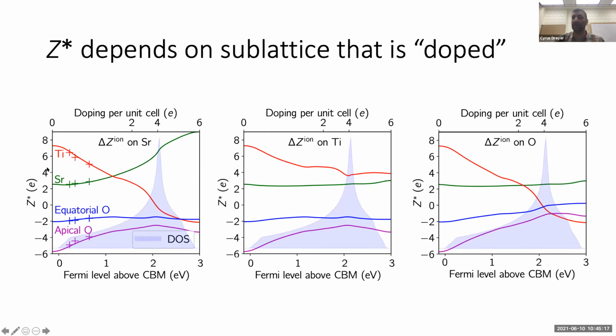One thing that is maybe interesting for the physics is that the behavior of the Born effective charges, again, depends significantly on where we assume the chemical doping occurred. So what I showed before is doping on the strontium, on the A site, for example, with lanthanum. We could also consider doping on the titanium site with, for example, niobium, or on the oxygen site. And in all of these cases, the Born effective charges change significantly.